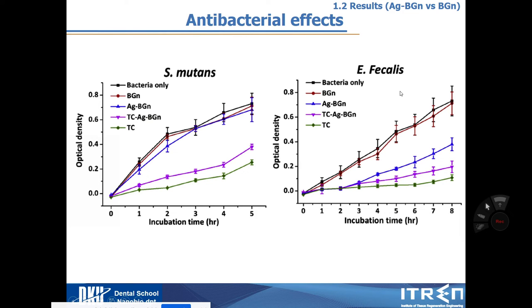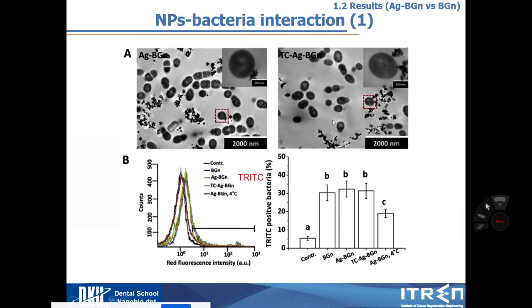And then I want to know how they have this antibacterial effect. So with bio-TEM, when I culture these bacteria with my nanoparticles, I want to look at how they interact with each other. Firstly, I expected that the nanoparticle could penetrate the bacterial membrane, but here I cannot see any nanoparticle inside the bacteria. So the nanoparticle can only attach to the bacterial membrane, with or without tetracycline. And then I want to quantify how many bacteria interact with the nanoparticles. So approximately 30% interact with each other between bacteria and nanoparticle.